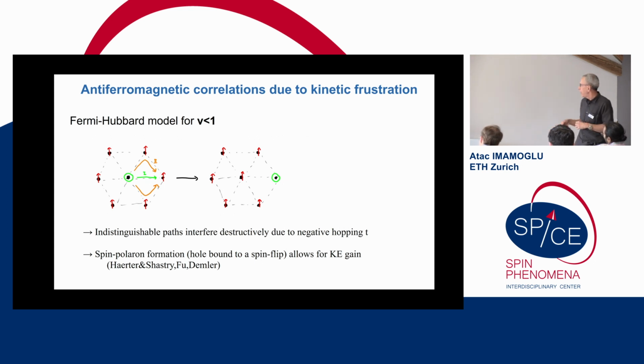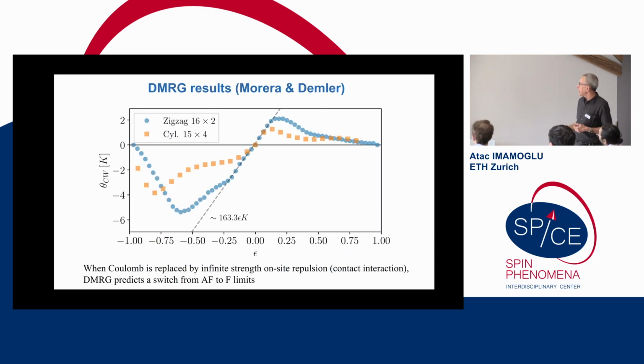Okay? So this is exciting, and these are the DMRG calculations from Eugene and Ivan, which indeed show, in the limit of infinite on-site repulsion U, boring behavior at nu equals 1, ferromagnetic correlations on the doublon side, and antiferromagnetic correlations on the hole doping side.